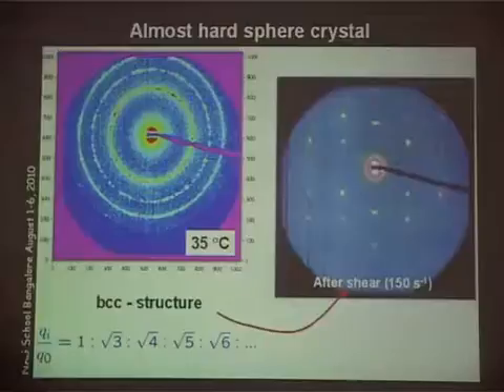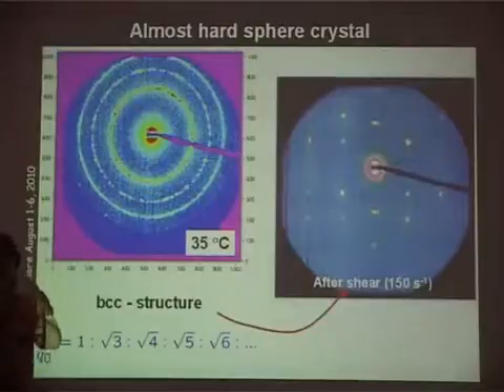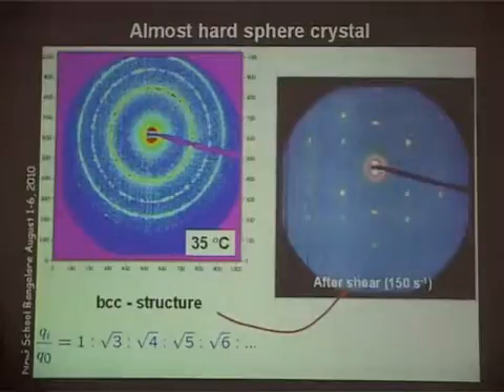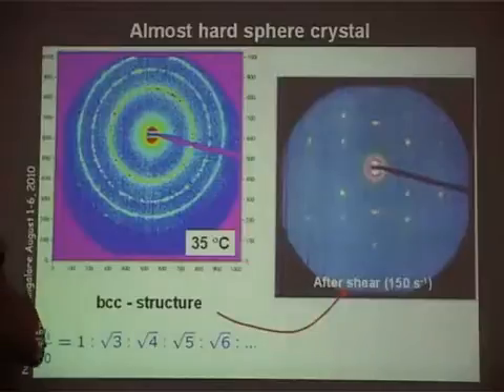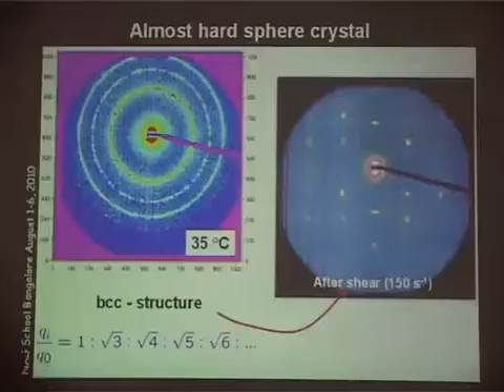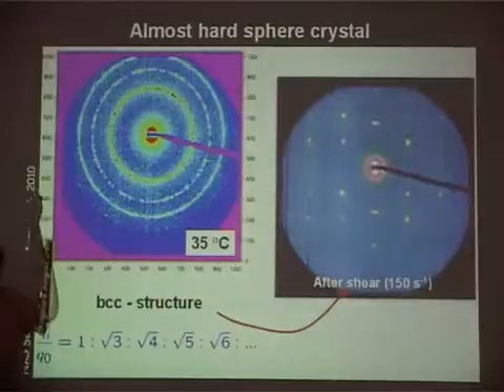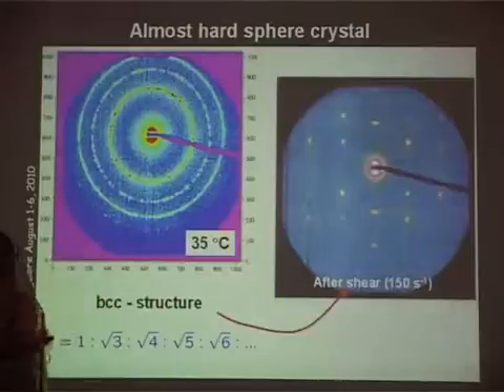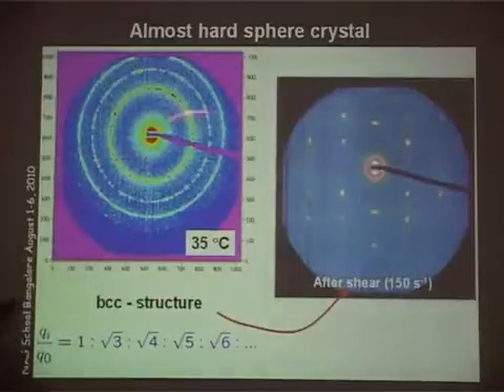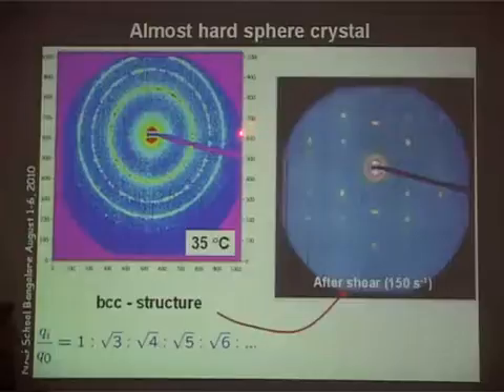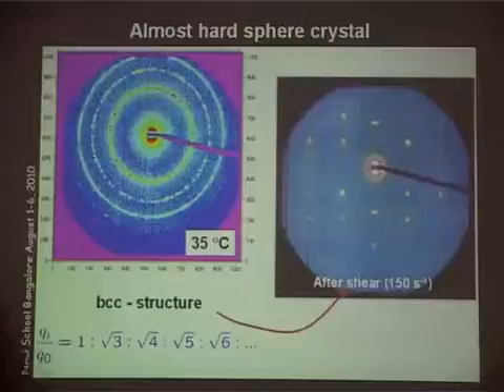So I have shear melted the micelles themselves. The whole thing becomes liquid. Because I put a lot of energy into that, the moment I stop, it goes completely back. Do you still maintain shear? No, I stop the shear. So I stop my rotation. It becomes stationary, and I need at least a few seconds to measure. I stop, I measure, I get this powder crystalline.